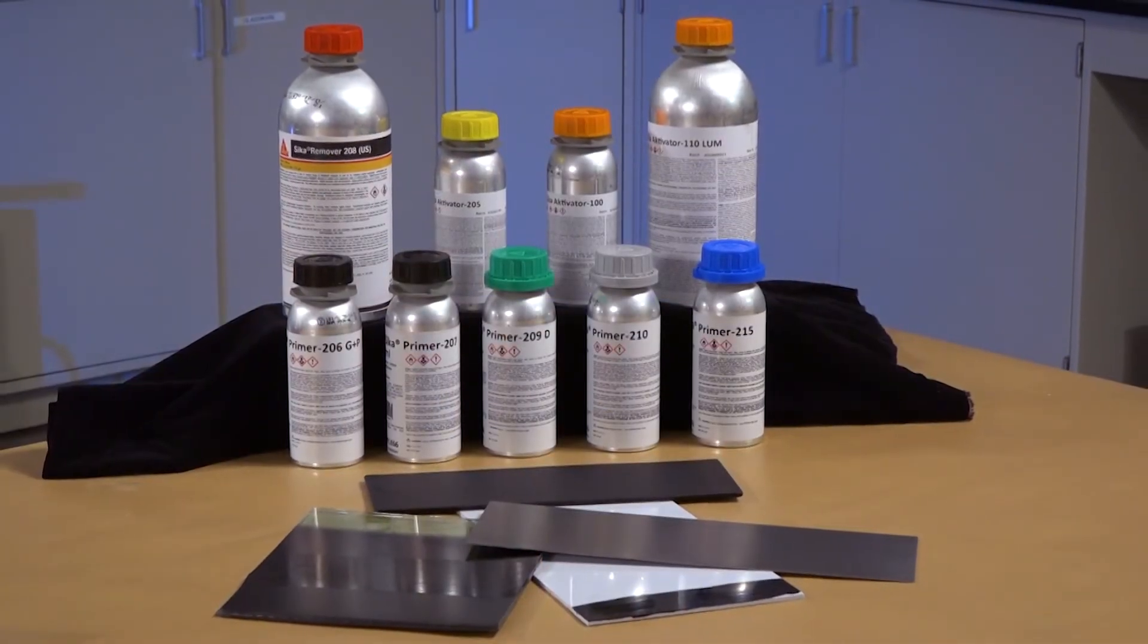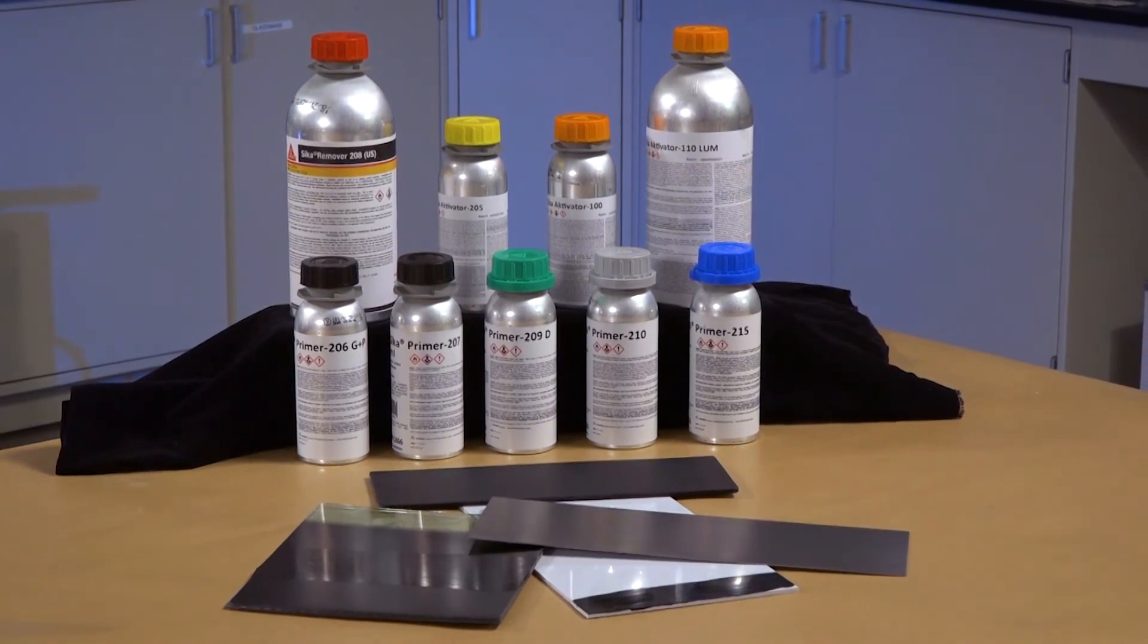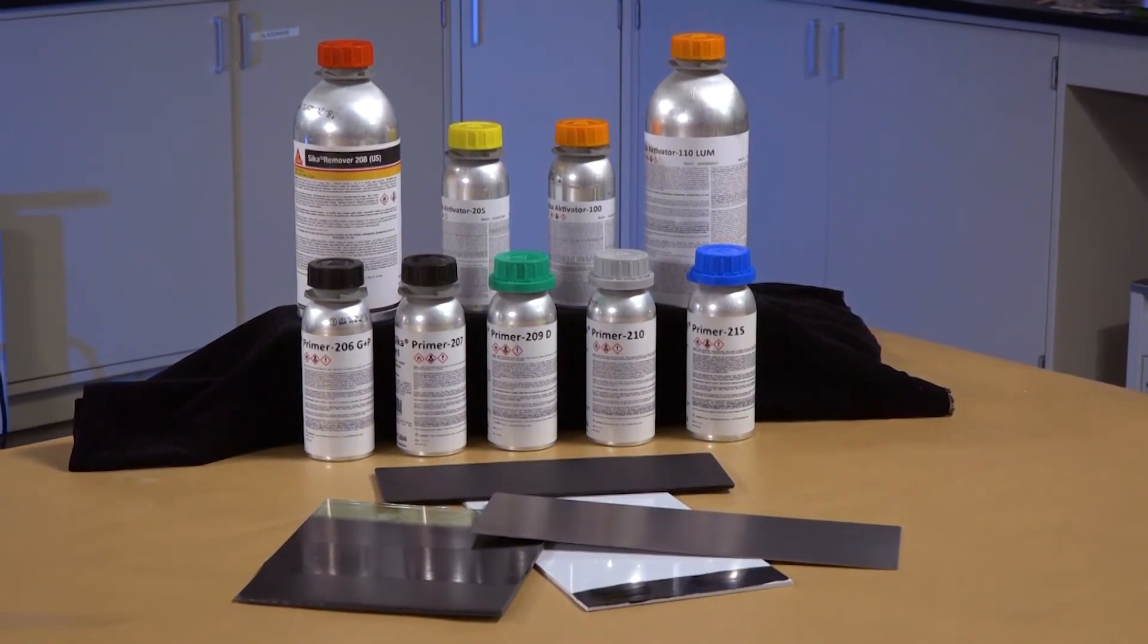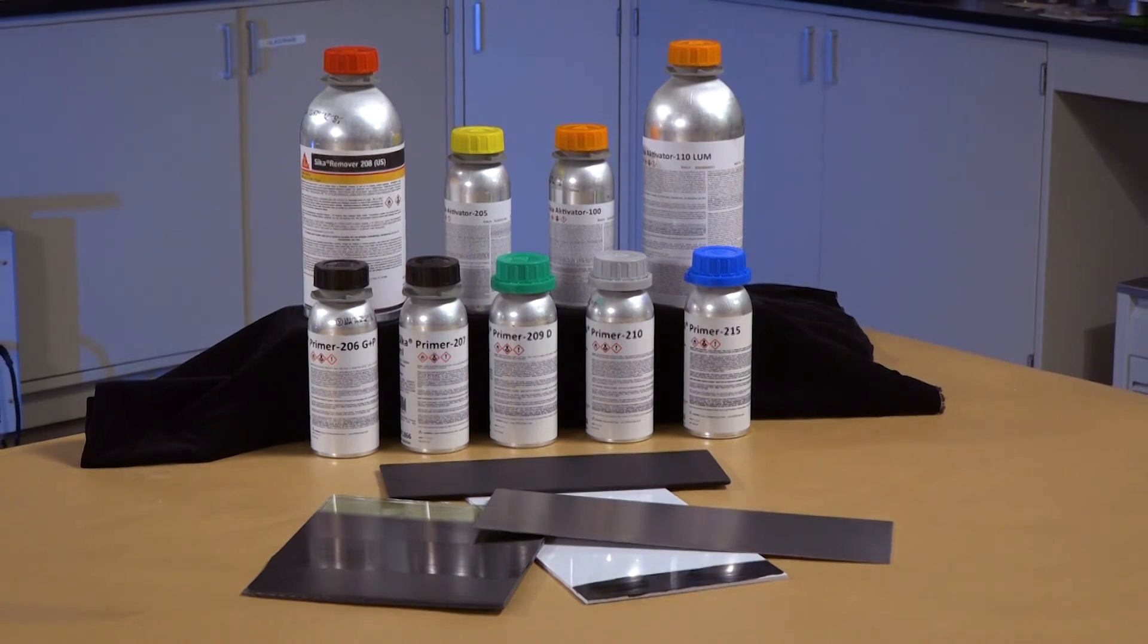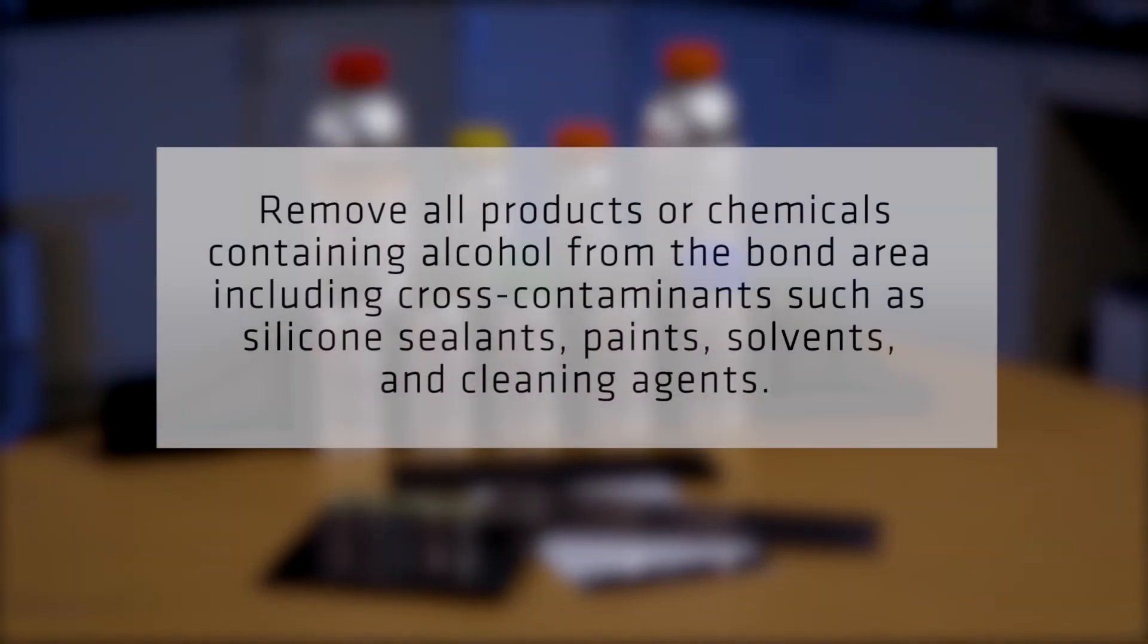Surfaces which have been treated with activators and or primers must be protected from contamination prior to application of the adhesive or sealant. To avoid cross-contamination, incompatible products such as silicone sealants, paints, solvents, in particular chemicals containing alcohol, and cleaning agents must be kept away from the bond area.